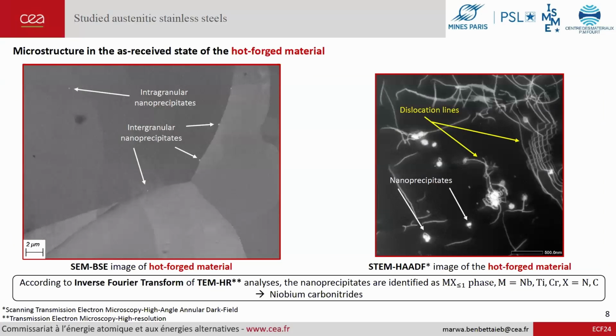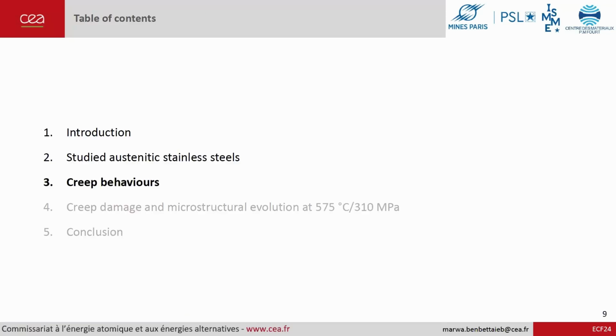In this image of the niobium-rich alloy, we can note at the as-received state the presence of intergranular and intragranular nanoprecipitates that are also highlighted in TEM analysis. These nanoprecipitates are identified as niobium carbonitrides, and we can also see some dislocation lines observed at the as-received state of this niobium-rich material.